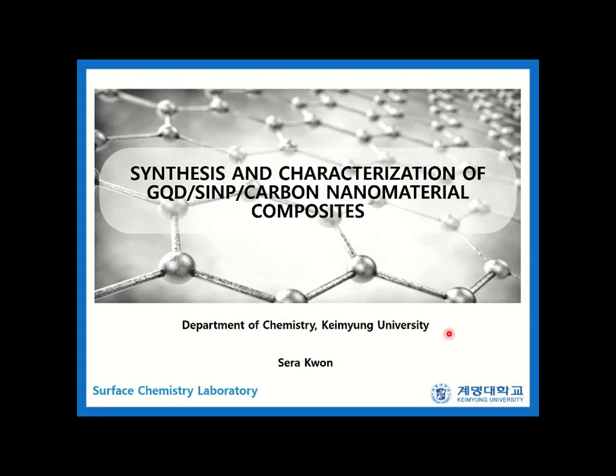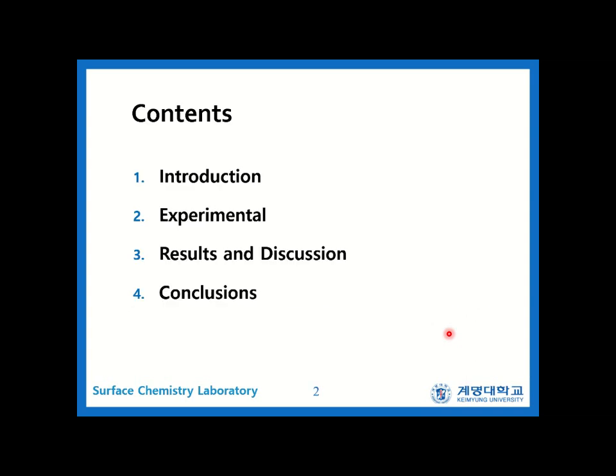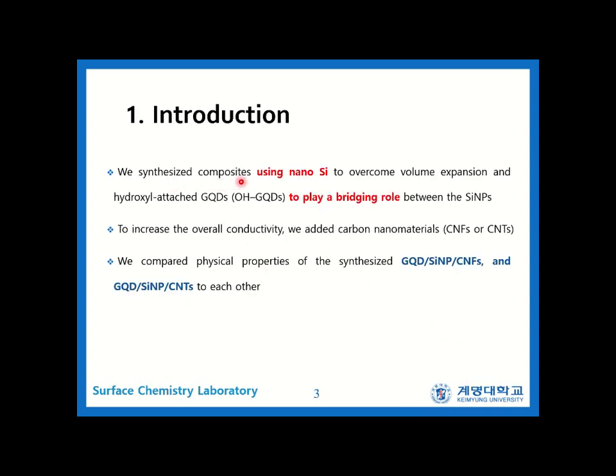Hello. I will discuss the synthesis and characterization of graphene quantum dot silicon carbon nanomaterial composites. We synthesized the composites using nanostructured silicon to overcome volume expansion, and the hydroxyl-attached GQDs to play a bridging role between the silicon particles. To increase the overall conductivity, we added carbon nanomaterials, and then we compared the physical properties of the synthesized GQD silicon CNFs and GQD silicon CNTs to each other.